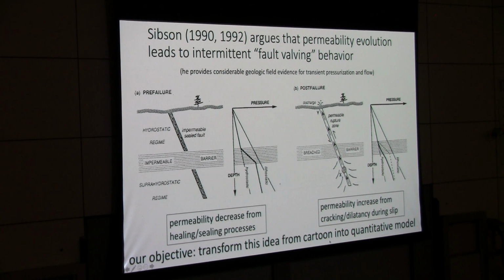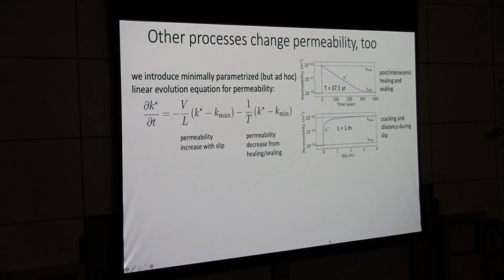This was a cartoon, and our goal was to transform this into a quantitative model. So we introduced some very ad hoc, but I think minimally parametrized permeability evolution models. We have permeability evolving with slip L via slip velocity. So V times T is slip. So permeability evolves towards a maximum value over some slip distance L. And then it also evolves towards some minimum value over some time scale T. Reality is a lot more complicated than this, but this serves to get us started. So we'll take this healing time to be of order a couple decades. There's some constraints on that. And then we'll put this slip evolution distance to be around a meter